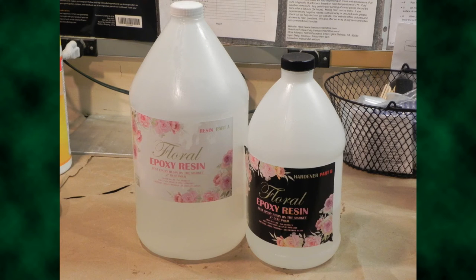Floral deep pour resins are a different formula. These tend to cure, producing lower heat over a longer time. They are also typically a different ratio, in this case 1-to-3, requiring 1 part hardener to 3 parts resin. The viscosity is much, much thinner, allowing for bubbles to work their way out of the resin over a longer period of time. Be aware that this curing time can take days. You will have to be patient, so there is a trade-off. There are many other brands out there with even more specific uses, depending what you want to achieve.